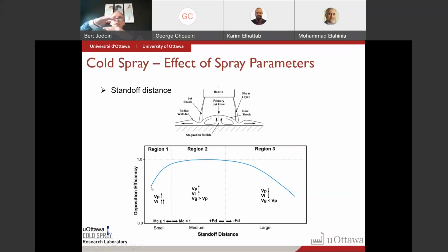If you move a bit further away your nozzle, now your particles will have more time to accelerate. The shock wave here will not be as strong, and you're going to be able to get a better deposition efficiency. You have a sweet spot where you almost get rid of that bow shock wave at the substrate and the particles get a very high velocity. If you move way too far from the surface you want to coat, now the jet velocity drops and the particle velocity drops, and then you're going to start to see a decrease in the deposition efficiency.